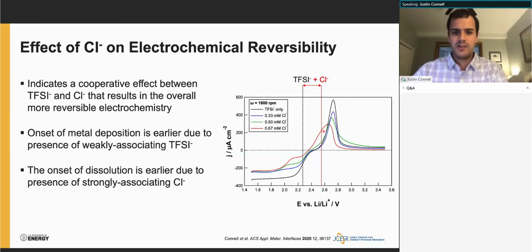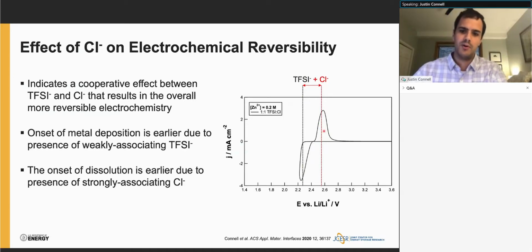And so if we then sum the contributions, this is what leads to the overall more reversible voltammetry that we see in the bulk plating and stripping behavior. And you really wouldn't have been able to rationalize this if you hadn't gone to the dilute case and been able to pick out the individual contributions of the ions. Now that said, this is at this point a little bit of speculation based just on voltammetry.